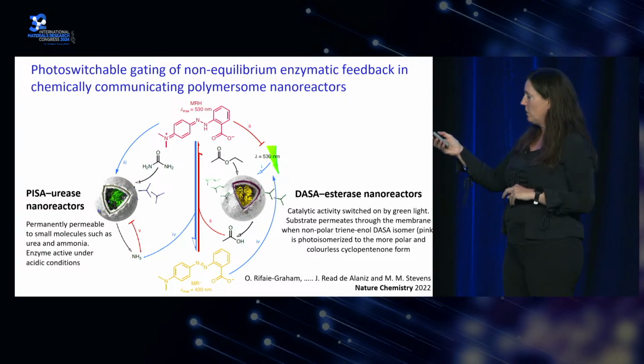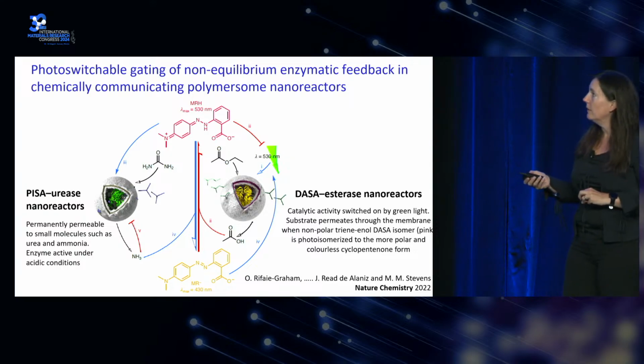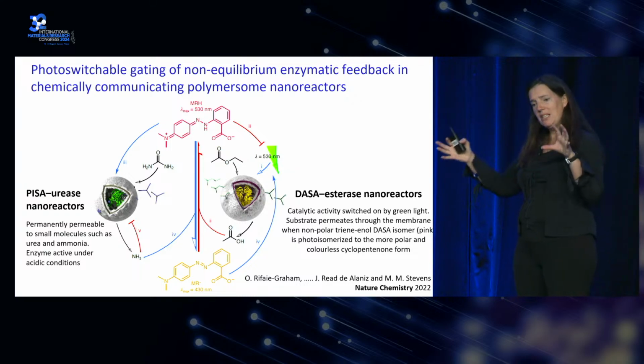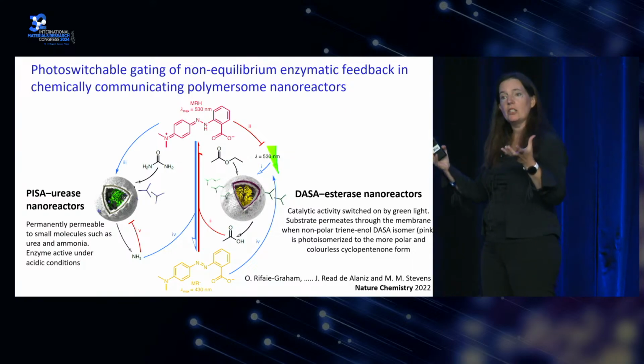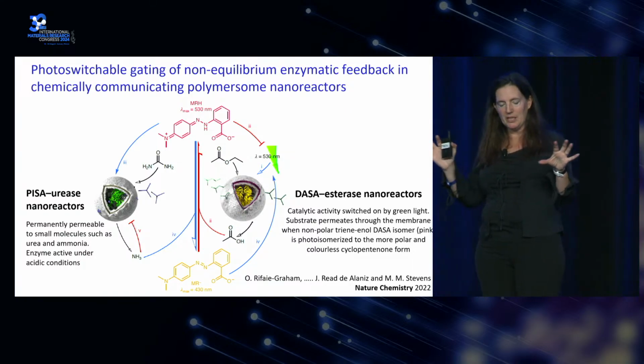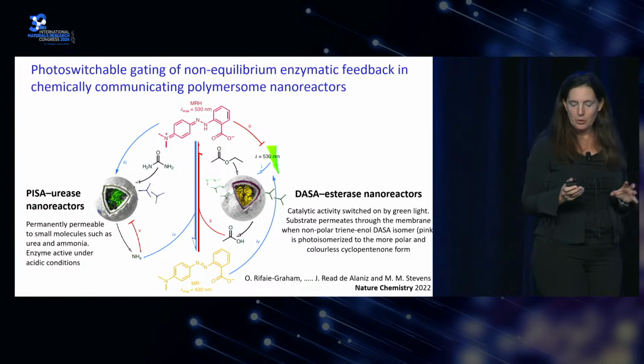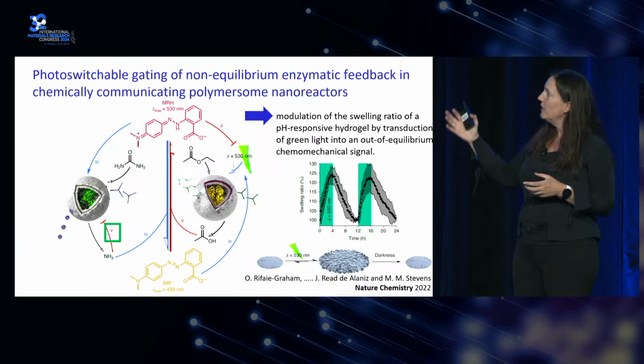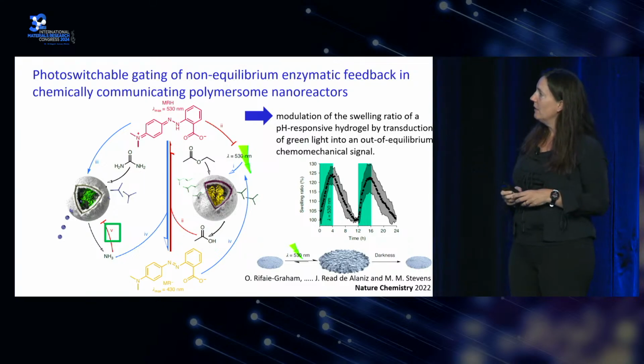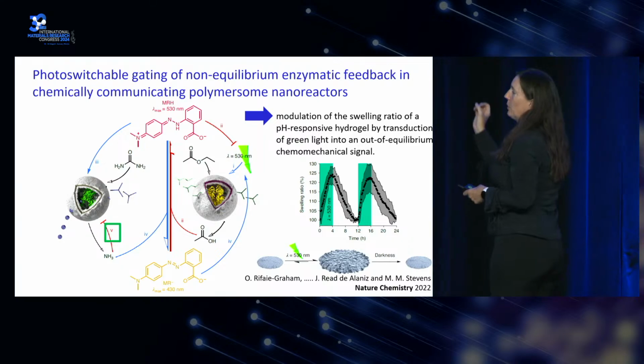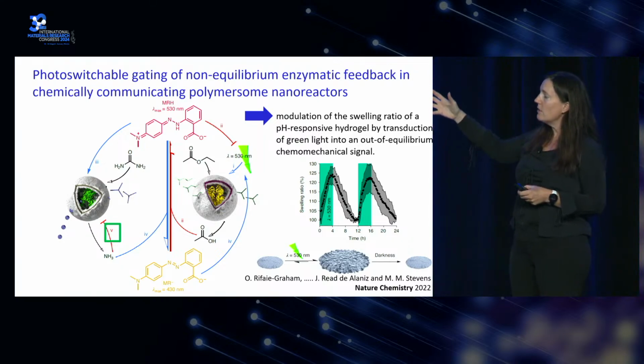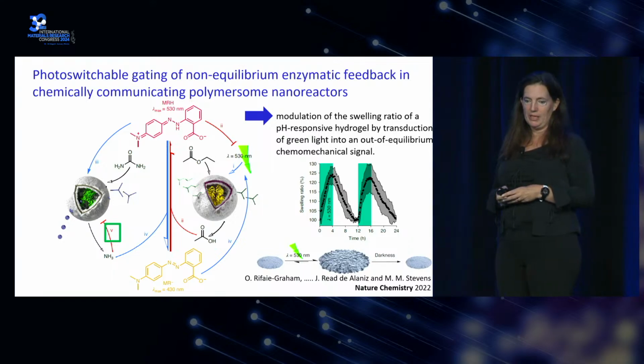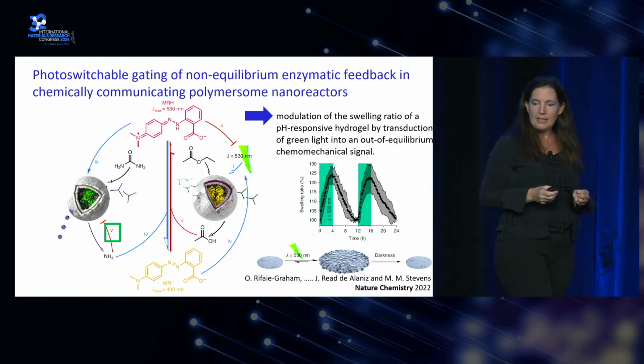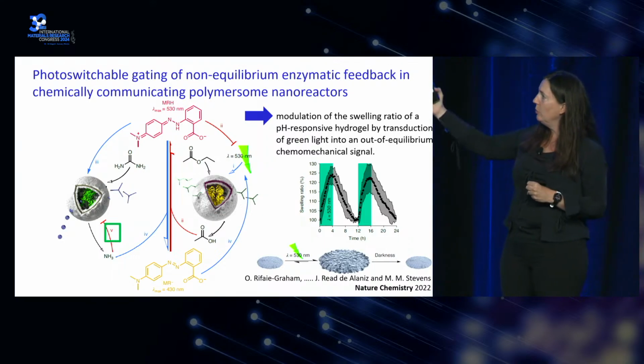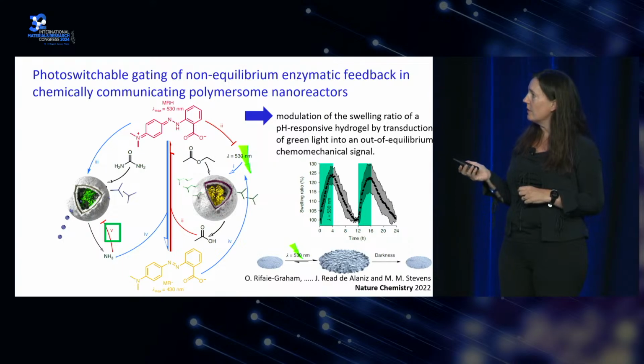And we can get this photo-switchable gating of non-equilibrium enzymatic feedback. And what you end up being able to do with these systems is actually to control the pH of the environment. So it starts off very fundamental, thinking about artificial organelles, maybe soft robotics. And then the fact that you can control the pH through light, through the activity of these enzymes, means that you can actually do chemomechanical work. And so what we did is we put these particles in the presence of gel systems that could swell and deswell in different pHs. And now those systems can get activated by light through the communication through our polymersome-based systems.